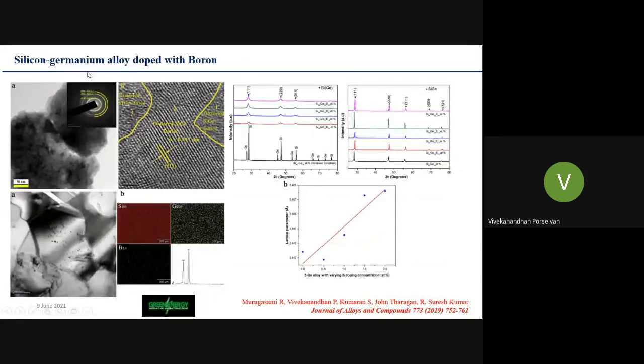And in the silicon germanium alloy doped with boron, we can see a higher reduction in the grain size. We can clearly see the atoms arranged in order, in different planes, in the silicon germanium alloy. This is a bulk scale of the alloy, and this is the variation in the lattice parameter due to the boron doping.